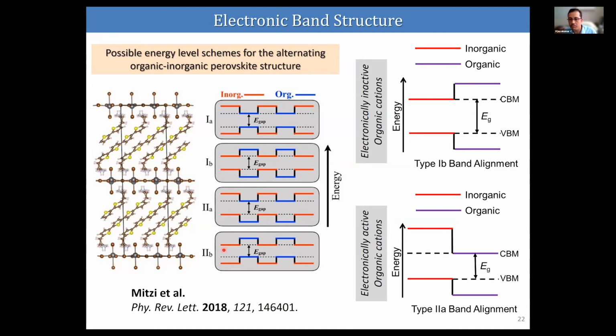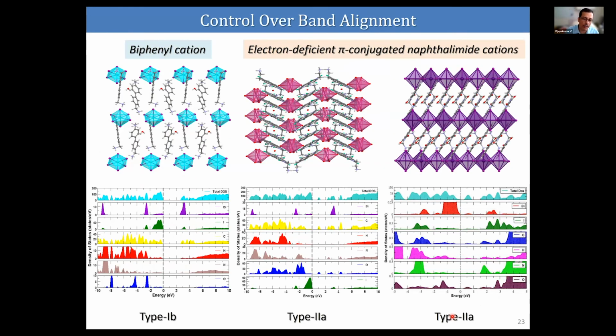So if you are using an electronically inactive organic cation, you will end up with a type 1B band alignment. And we found that if you are using an electronically active organic cation, you can get a type 2A band alignment. And it was proved by making 3 materials. We made 3 bismuth halide perovskites, having biphenyl cation, that is the first one. And second and third are the naphthalene derivatives. This is naphthalene diamine, and this is naphthalene monoimide, and this is diimide.